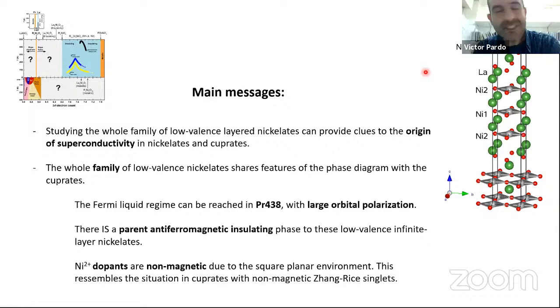I mean, there are some changes. I saw a paper recently that discusses all the series of the lanthanides, and that there are some trends that you can understand, but the essential physics, the essential electronic structure is not changed. You can have some differences in the position of the bands, in the bandwidth, certainly, that will give you some second order effects, but there is no trace, no indication that the substrate effect, that the strain effect would be the driving force, the driving role towards superconductivity. There is no indication of that. Okay, thank you very much.